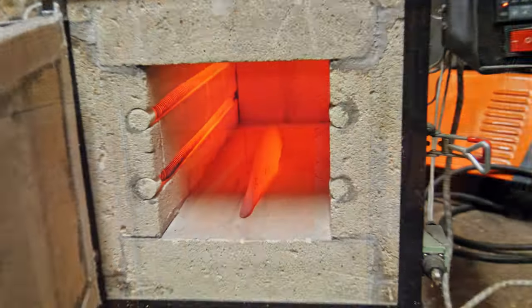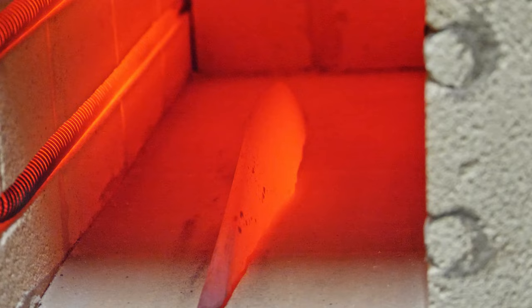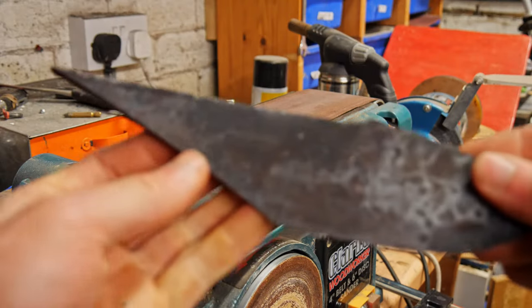I set the heat treatment oven to 800 degrees celsius which it heated up to quite quickly and then I just let it soak there for a few hours and then let it cool down really slowly overnight. This relieves all of the internal stress within the metal.